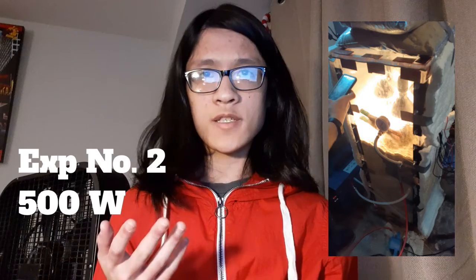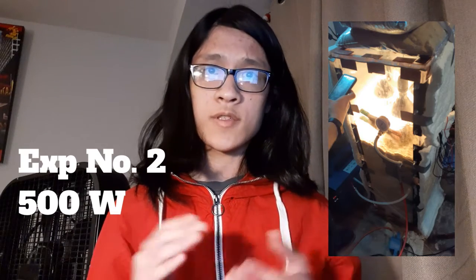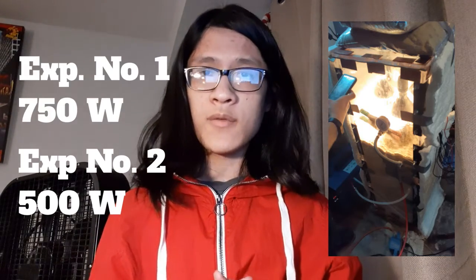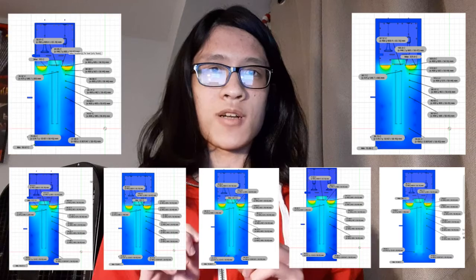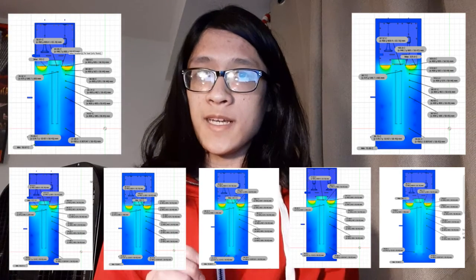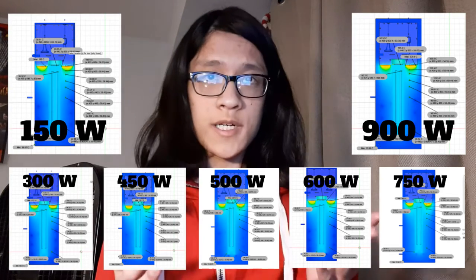Our experimental study found that there did persist a significant temperature differential across the thermoelectric generator system through an applied heat source. For our project, we utilized results from two in-situ experiments with our testing rig, one of which was conducted with 500 watts of applied heat power, the other of which was conducted with 750 watts, and we also utilized results from 7 CAD model simulations, with applied heat ranging from 150 watts to 900 watts.